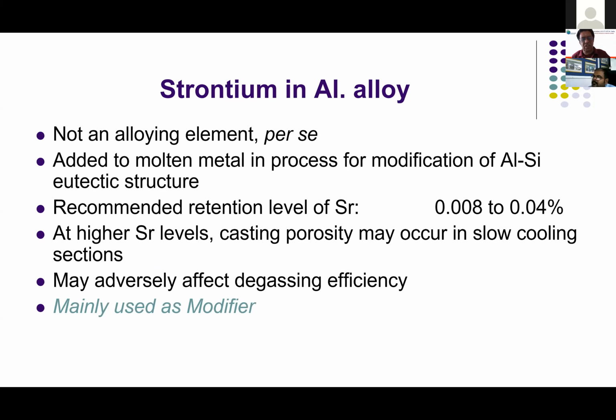Earlier we used to use sodium as a modification agent 15, 20, 25 years back. It has got its own bad environment effect and all. Slowly the usage of sodium has gone down. Strontium has replaced it. Strontium essentially modifies the way silicon dissolves and appears in the microstructure. Silicon in the form of noodles and silicon in the form of globular structure, rounded edges, gives higher strength, higher surface. Therefore, the strontium does a very good job in this area. 0.008 to 0.04% of strontium modifies the silicon structure. So therefore, in GDC and LPDC, where you require a good modification, instead of sodium, we go for strontium.